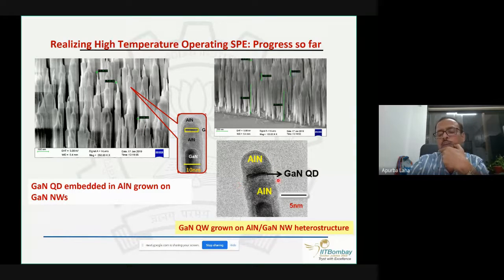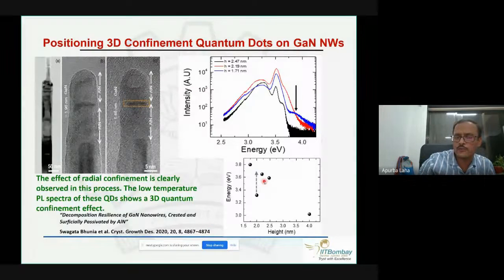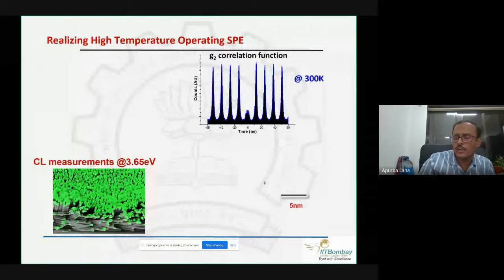Now, this is a typical 3D confined structure. If you look at this horizontal direction, it is almost less than 5 nanometer, which is below the confinement range or excitonic Bohr radius for gallium nitride, and vertically you can control. So this way, we could create nanostructures or quantum dots that give us very strong confinement, and that we eventually showed here.